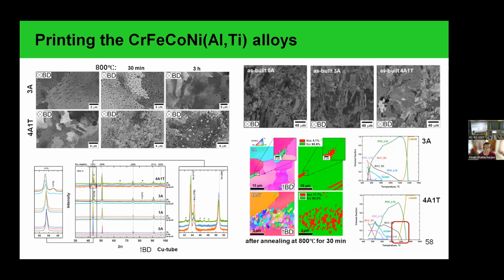So to understand exactly the fraction of these materials, there should be a set of EBSD tests in both directions at different magnifications. In our study, we just demonstrated that there is a BCC phase and tried to understand the fraction of this BCC phase in comparison with the material with titanium. We concluded, according to the EBSD analysis, that it's approximately 4%, but I can't guarantee this number strictly.